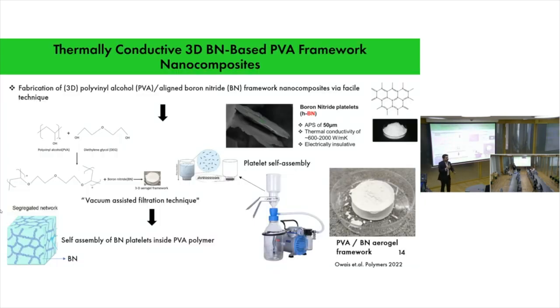The purpose of fabricating this 3D structure is that in a 3D structure, we have high thermal transfer efficiency. An aerogel, for example, can be used as an insulating material, to transform from thermally insulating to thermally conducting material. In this regard, we use boron nitride platelets. Boron nitride, as you all know, is highly thermally conductive, with a thermal conductivity ranging from about 600 to 2000 watts per meter Kelvin, and it is also very electrically insulative. This is very pertinent for thermal management applications where electrical insulation is required. In my project, I use PVA and then use some plasticizer to introduce some plasticity inside the framework 3D aerogels.